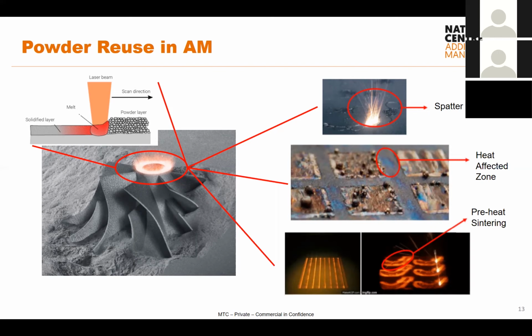Now, again, because you pre-sintered, there's a chance of that raised temperature, therefore higher oxygen content in the particles locally, and potentially, because you've sintered, potentially there's going to be a morphology distortion, and so again you're degrading the morphology of your particles. So these very nice spherical particles are no longer as spherical. Is that going to affect the way they flow and pack in further builds?